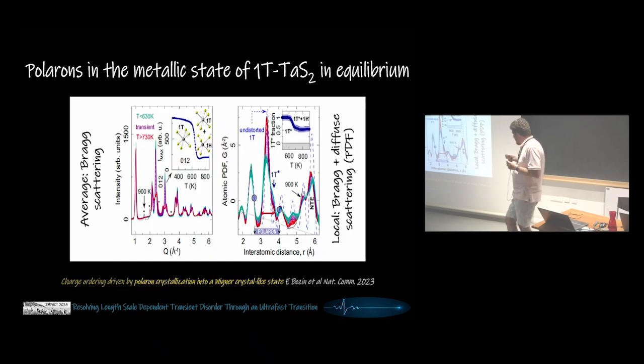So in equilibrium, these are just a few examples to demonstrate how it works. We looked at tantalum disulfide that I mentioned previously, and what one needs to know about the 1T polymorph is that that's a metastable state. So you start with the tantalum disulfide, you quench it, and so long as you stay below a certain temperature, you are in the 1T state. If you heat it up, you're going to violate metastability, and you're going to end up in some other polymorph irreversibly, unless you reset it by quenching again.